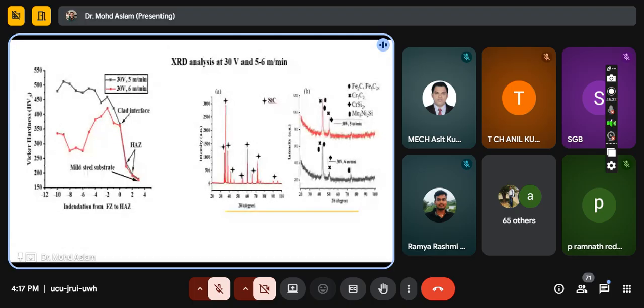So here some of the hardness tests were also conducted, and we have observed that the red color is showing 6 meter per minute, and the upper black one is showing 5 meter per minute. The problem is, what is the problem in the case of silicon carbide? When we are using a maximum percentage, more than 3%, 4%, 5%, with the steel matrix on a mild steel, it developed cracks when we conducted a hardness test. Easily it will develop cracks during the hardness test.